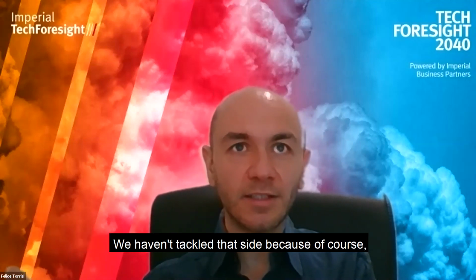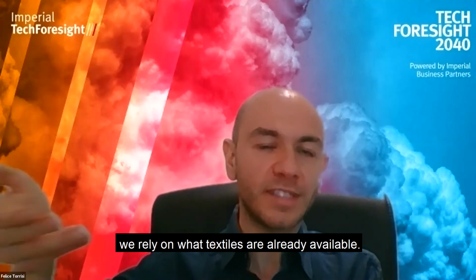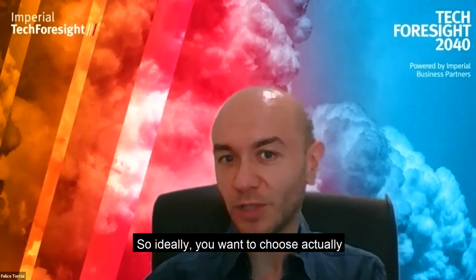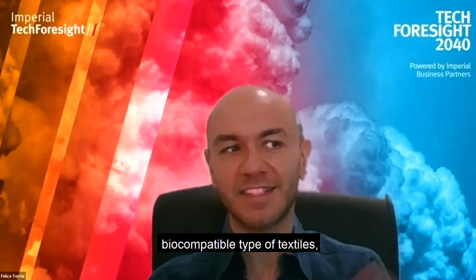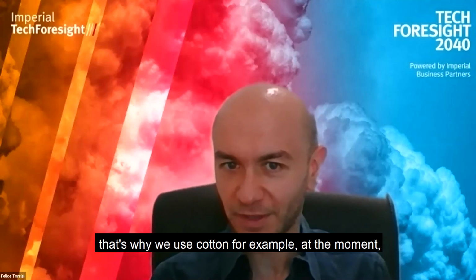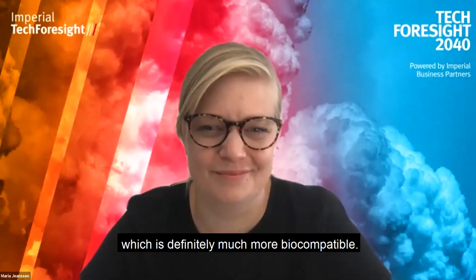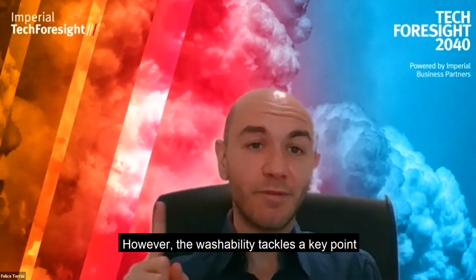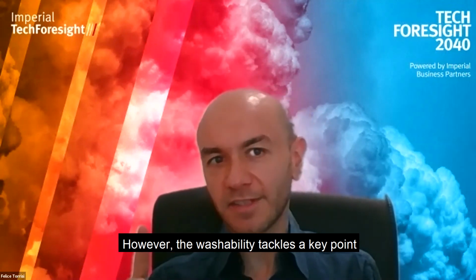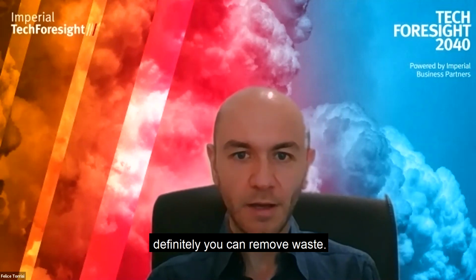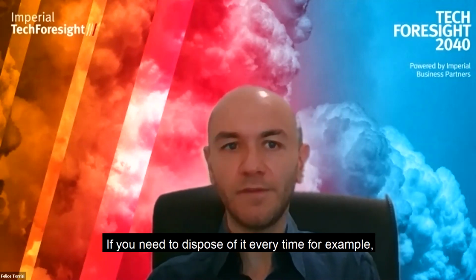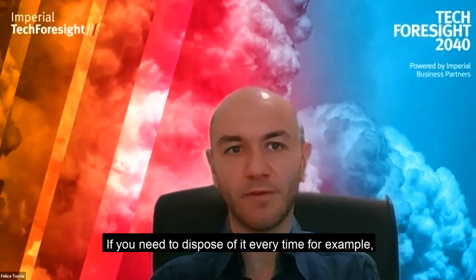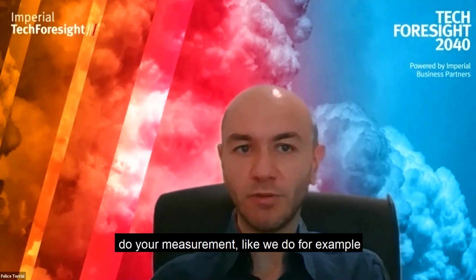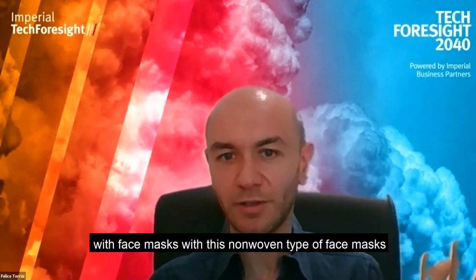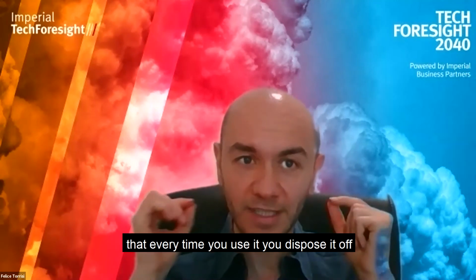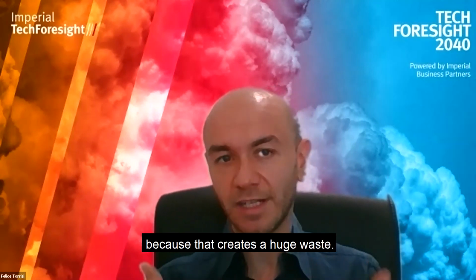In that case, the entire system needs to be biocompatible. We haven't tackled that side because, of course, we rely on what textiles are already available. So ideally, you want to choose biocompatible textiles. That's why we use cotton, for example, at the moment, which is definitely much more biocompatible. However, the washability tackles a key point, because if you can reuse it, definitely you can remove waste. If you need to dispose of it every time you do your measurement, like we do, for example, with non-woven face masks, that creates a huge waste.